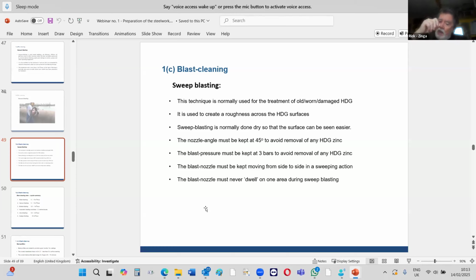So when you're sweeping, it's breaking up the hot dip galv and removing any loose flaky bits. It's removing little bits of zinc off the surface, making it rough, but it's not removing the thickness of the hot dip galv. You want to retain that. And this is actually a standard in Australia and New Zealand now, this method. So it's not only for repairing hot dip galv.